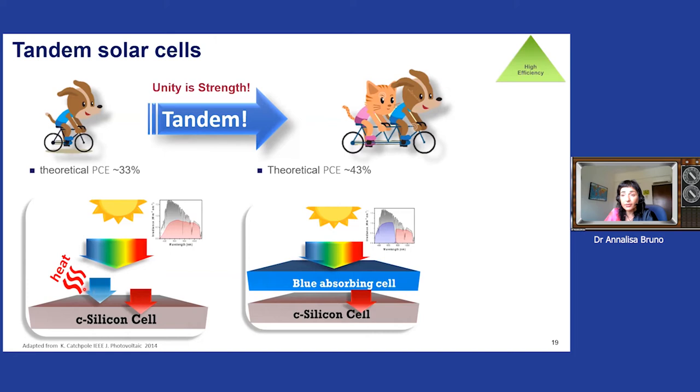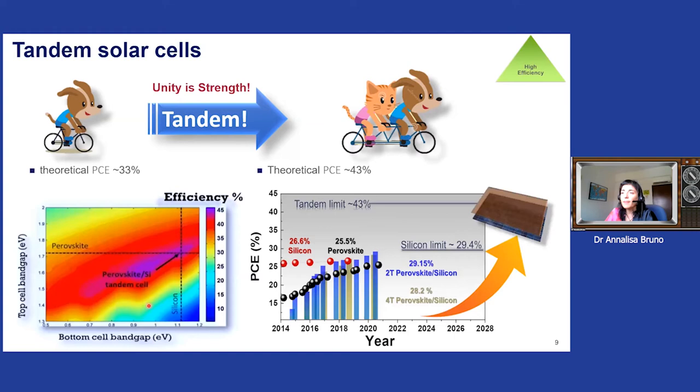So if we put on top of it a blue absorbing material, this can compensate for the blue region, and this radiation is not lost. So using the two cells in combination, there is a theoretical prediction that shows that with a proper tuning of both the top and the bottom band gap of the cells, we can reach efficiency above 43%. And this is a summary